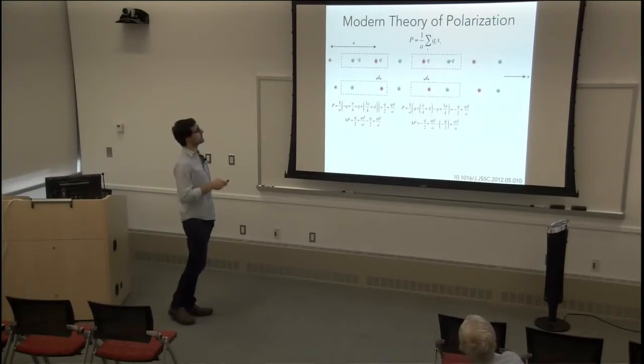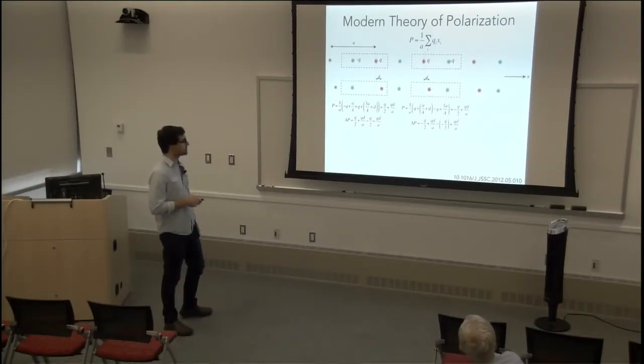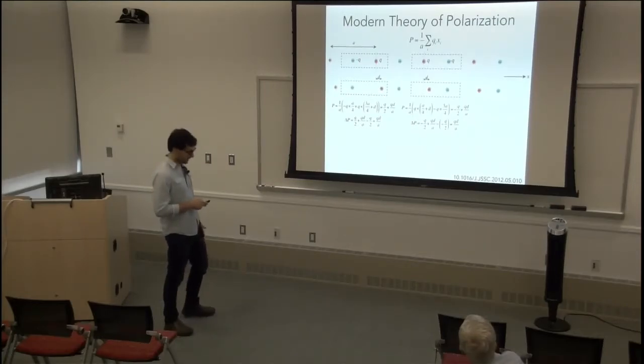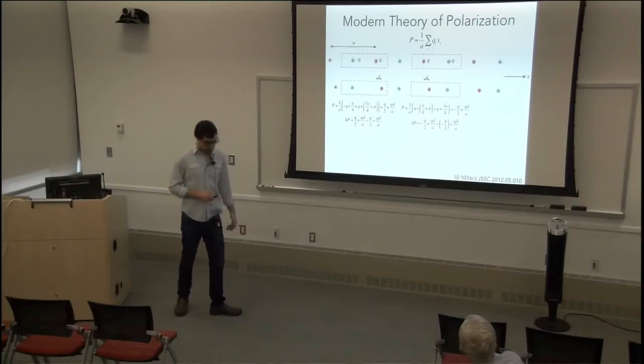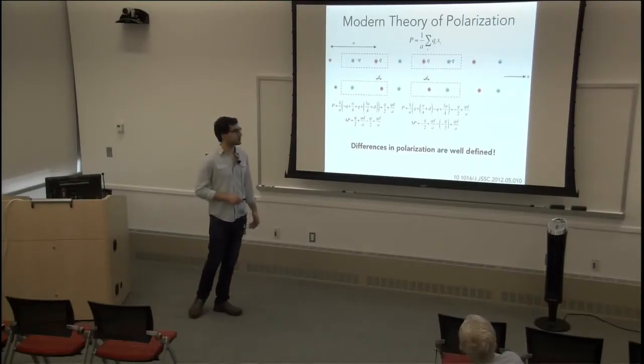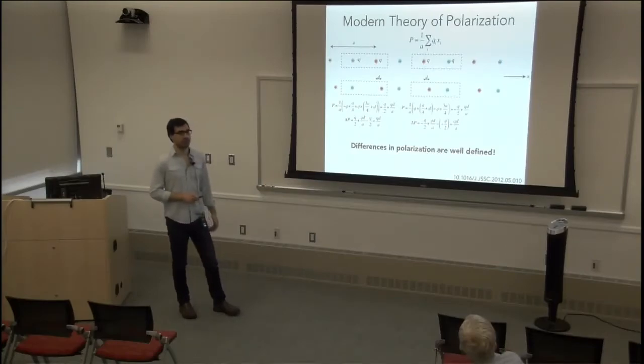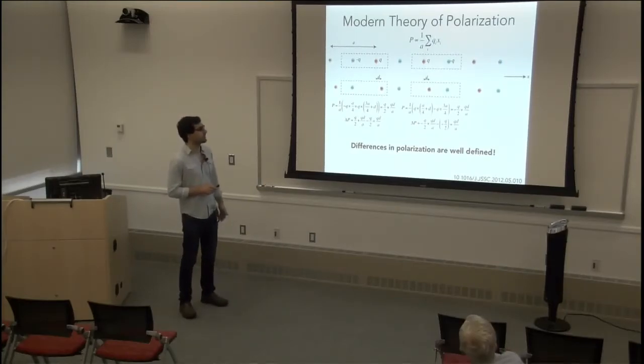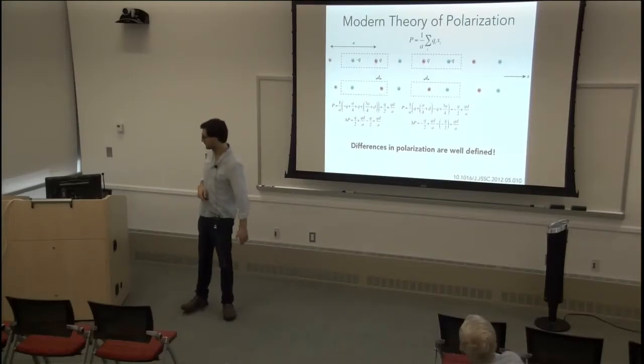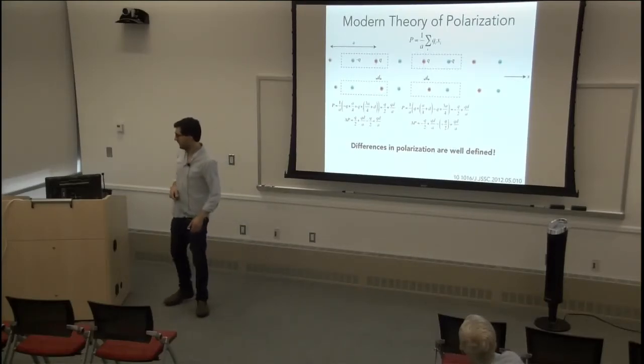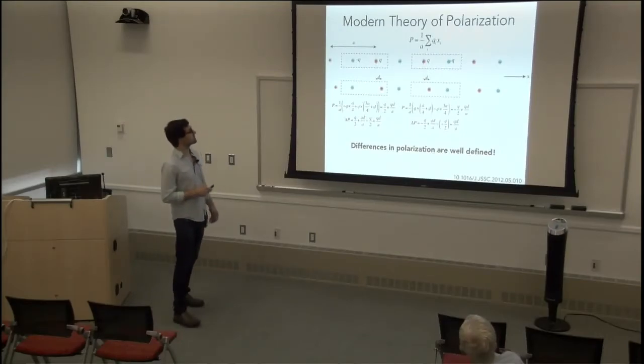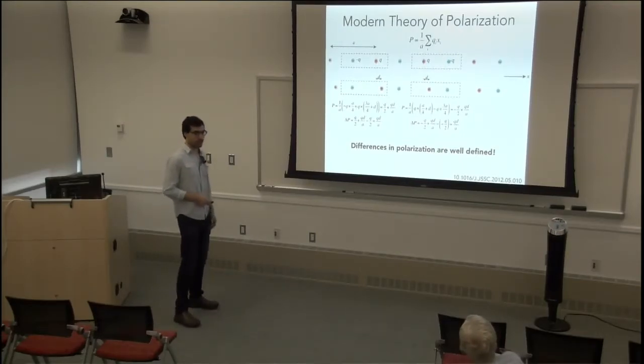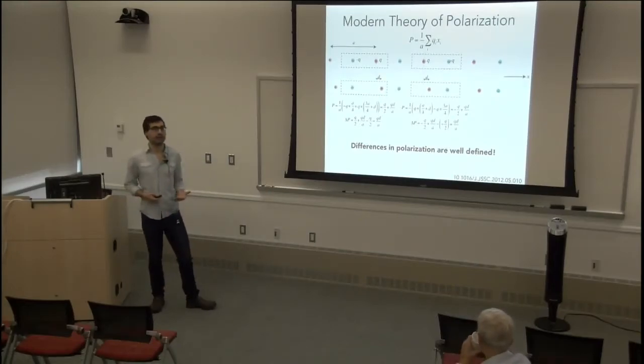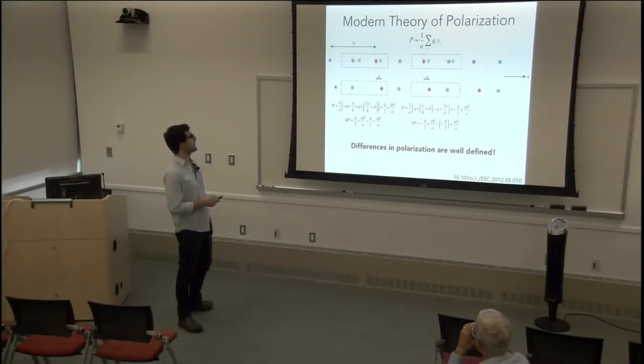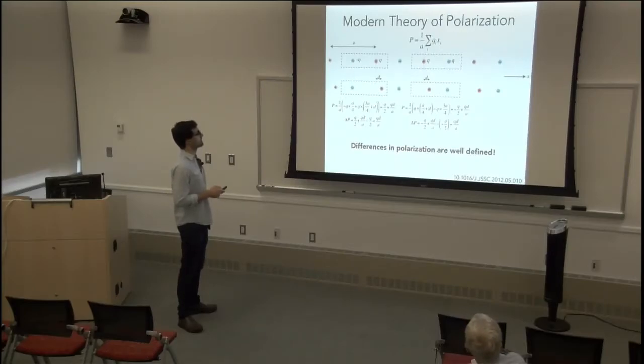What I care about is the difference. What's the change in the polarization? And as you see, for both cases, the change in the polarization is the same: QD over A. This means that only differences in polarization are well defined, and that's really how one should think about polarization in infinite systems, as opposed to, let's say, a molecule. Now, one more thing about polarization is that, of course, these things are point charges, and in reality we have electron clouds, and things are not all localized in one location.